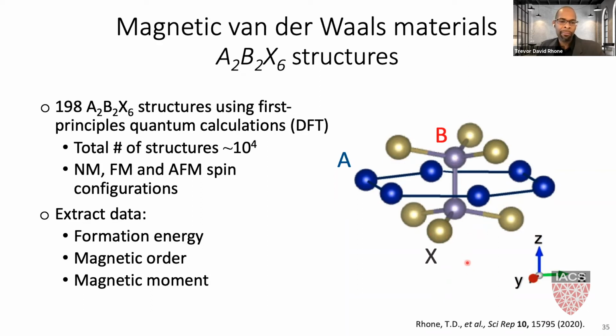If you decorate this lattice with all the possible combinations, you get about 10^4 different candidates. I chose 200 of those to perform my first principles quantum calculations, and I looked at extracting a few properties: the formation energy, the magnetic order, and the magnetic moment. It turns out that these 200 calculations took me about half a year on a supercomputer. So these can be relatively slow.